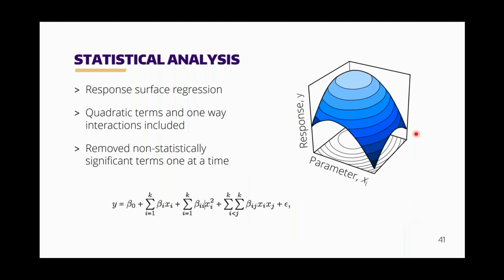So now I'm going to delve a little bit into statistics here, and what we did with this experimental design allows you to go through and look at a statistical analysis and quantify some uncertainty. And so I'm going to show you some plots from the resulting numerical model. We're showing you the mean surface, which has its own limitations, but at least gives you a sense for the way the space works. We took this data and fitted a quadratic model, which you can see what that might look like here. There's an error term, there's an interaction term, so do the variables interact with one another? You can have a squared term, so you can have some sort of plateau, and linear terms as well.